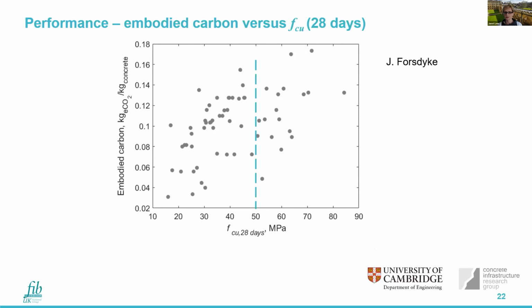So if we have a particular strength requirement, again, I've just picked something, say 50 MPa, you see that there are choices available within this, which have a higher embodied carbon or a lower embodied carbon. But the question is much more complex, because we've already been hearing about how if we have a column, it might actually be that the best decision, for overall reduction in embodied carbon, is to use a high cement content, but a much smaller volume of concrete. So these again are aligned to what we need to do structurally as well, as to which of these mixes is the best in terms of the overall system and reducing the overall CO2.